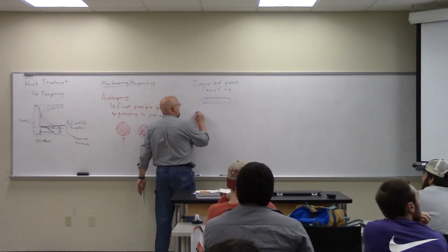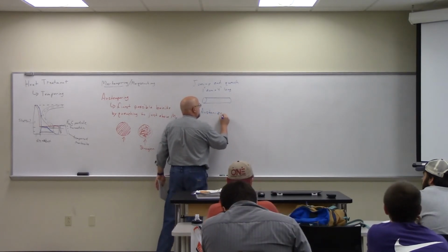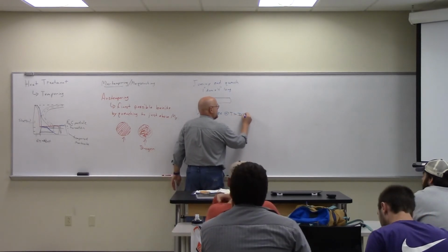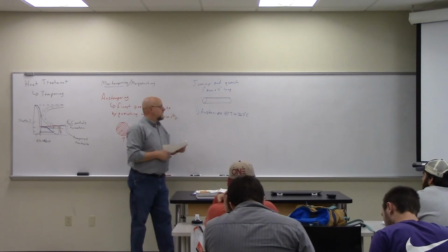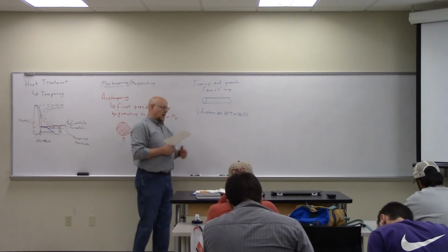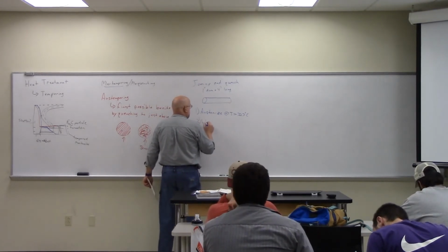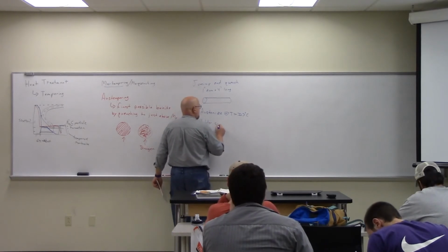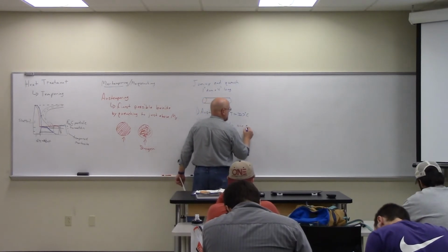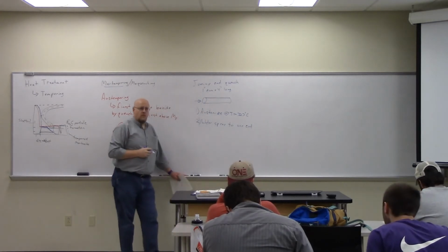Okay, so the first step here is to austenize, at a temperature greater than 727, so I have purely gamma material. And then the second step is to apply a water spray to one end. So I spray water at a very high volume to one end.